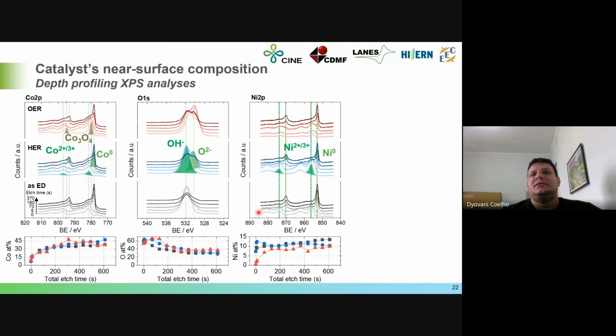And we can see the same. The surface is composed of oxides, nickel oxides, and underneath we can see the peaks characteristic of the metallic forms for the hydrogen evolution reaction and even for oxygen evolution reaction. So even after 24 hours of cycles applying 100 milliampere per square centimeter, the catalyst film is not completely oxidized. We have some metallic forms there.